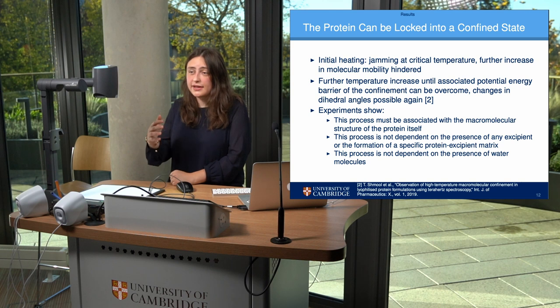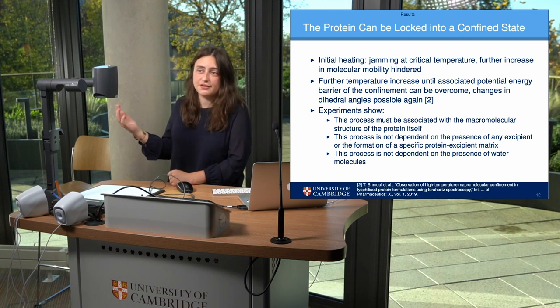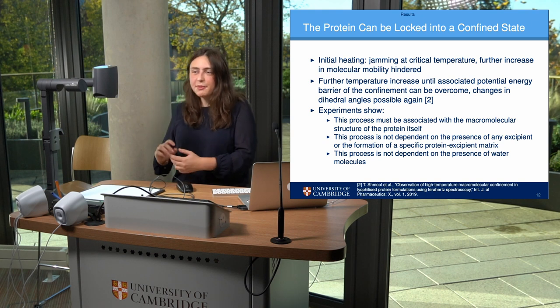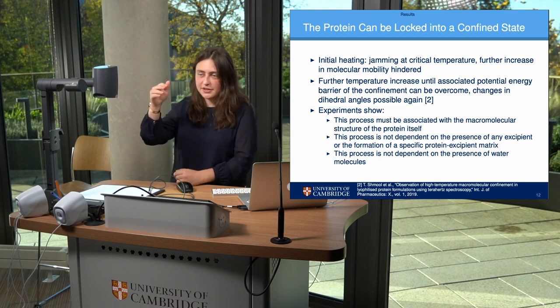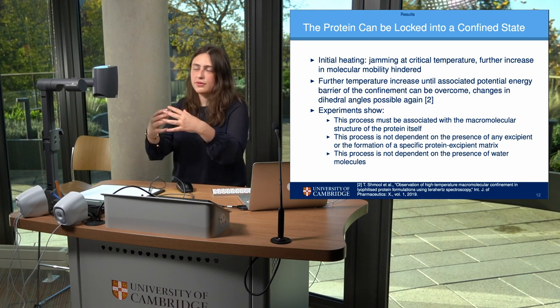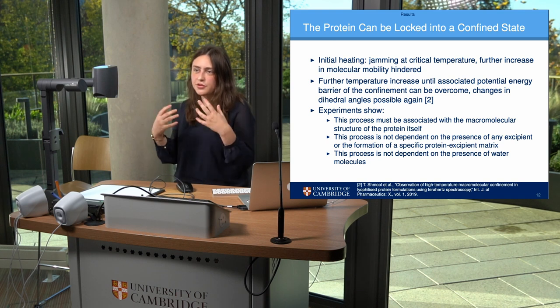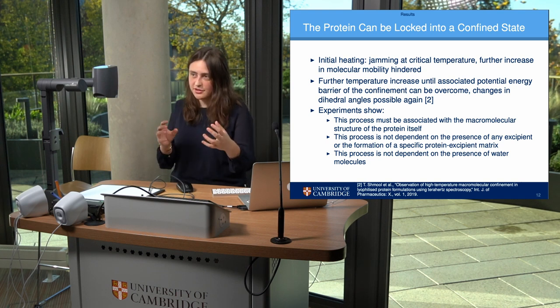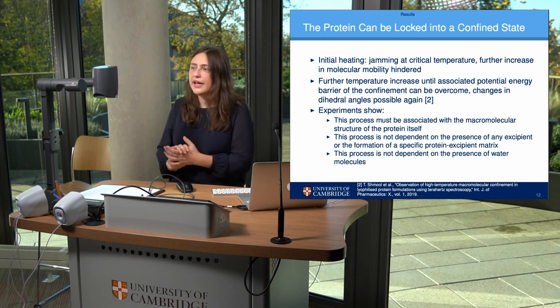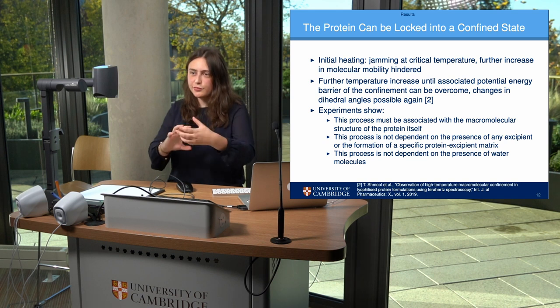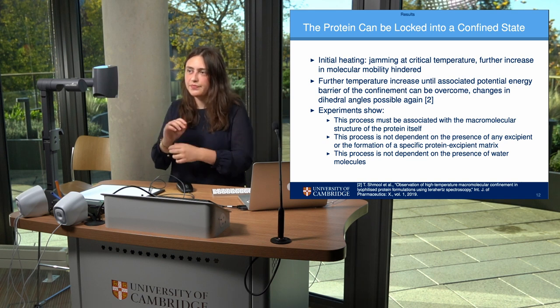In that case, the protein can move again and it is no longer jammed. The experiments have shown that this process is associated with the macromolecular structure of the protein itself. We can say that because we have measured all the samples containing sucrose, samples containing a bit of sucrose, and samples containing only the protein.